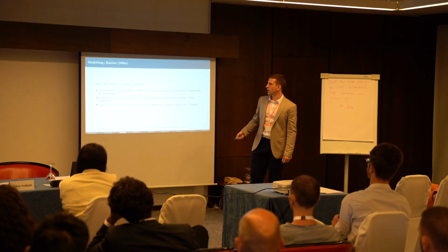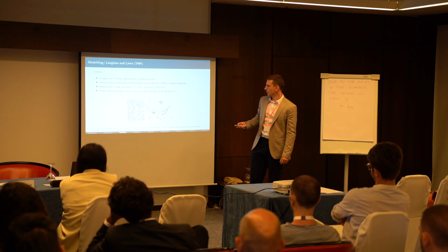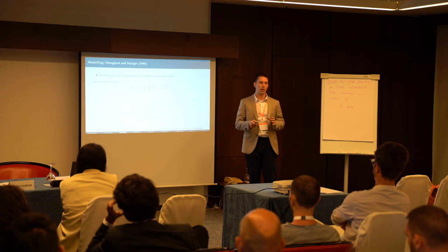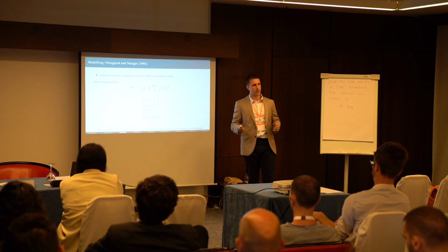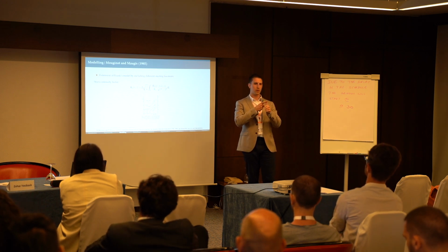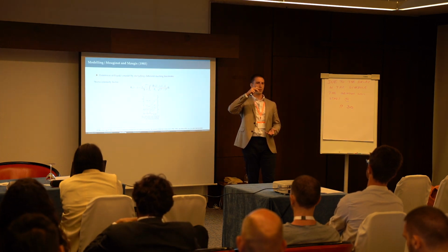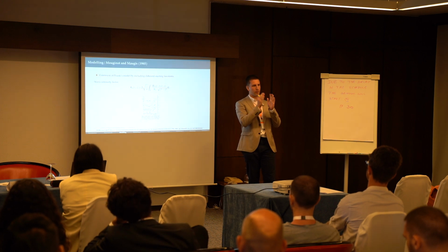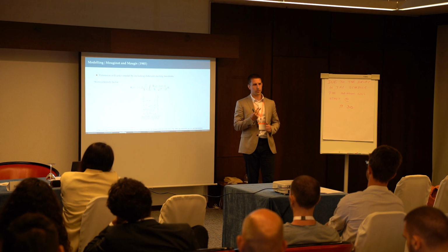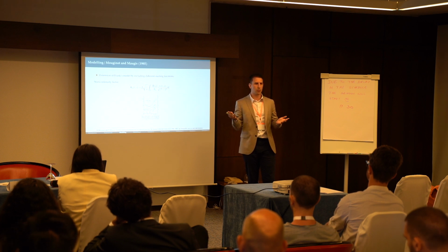So people were modeling that for almost 70 years. And the original complaint was that the Weibull statistics or the flaw statistics is not usable because, on one hand, you would observe with smaller balls a bigger scatter in forces, because you have a smaller area where you need to find defects, so it would be harder to find them. The second objection is that your effective volume or effective area also depends on the ball radius, so how do you use it?